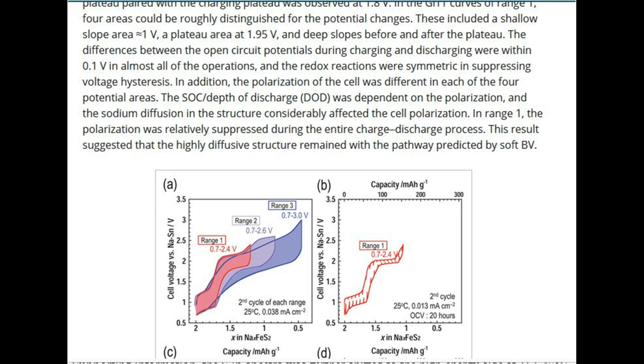In addition, the polarization of the cell was different in each of the four potential areas. The SOC/depth of discharge, DOD, was dependent on the polarization, and the sodium diffusion in the structure considerably affected the cell polarization. In range 1, the polarization was relatively suppressed during the entire charge-discharge process. This result suggested that the highly diffusive structure remained with the pathway predicted by softBV.